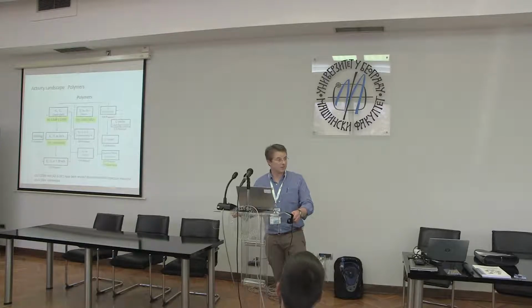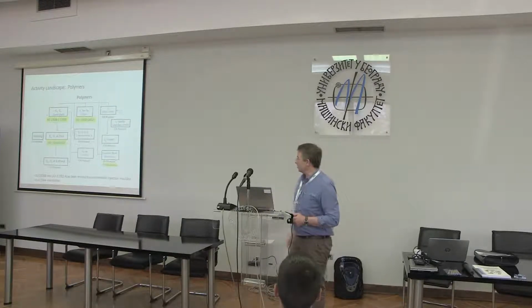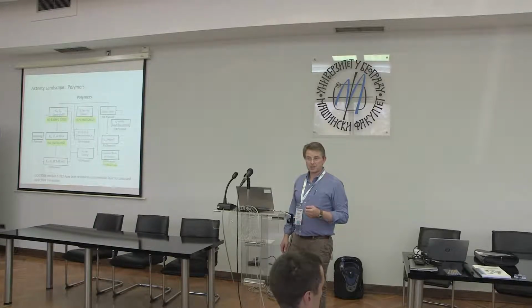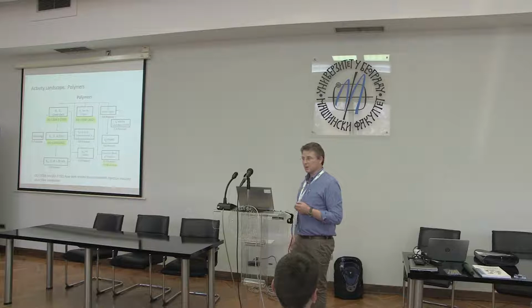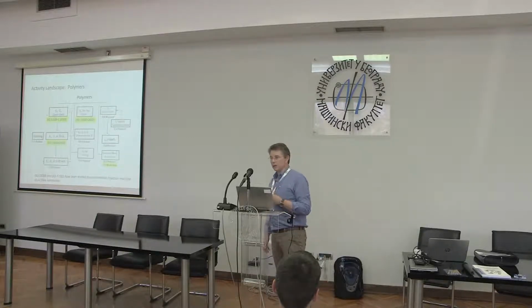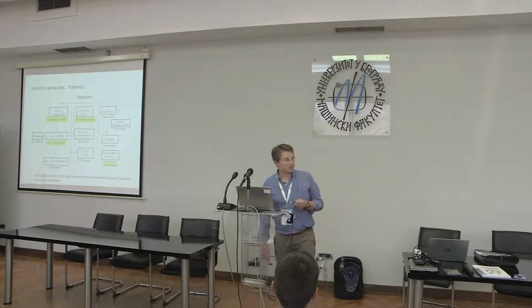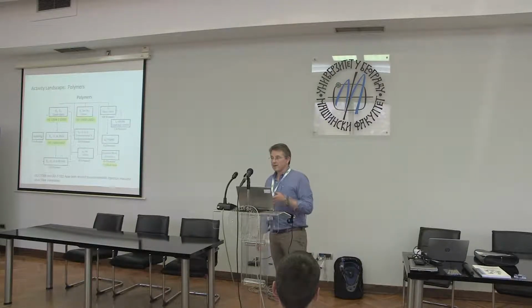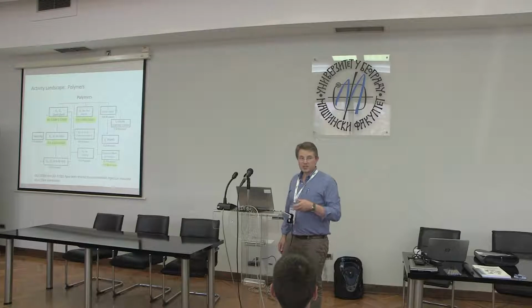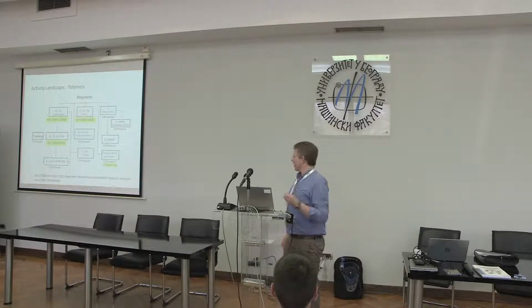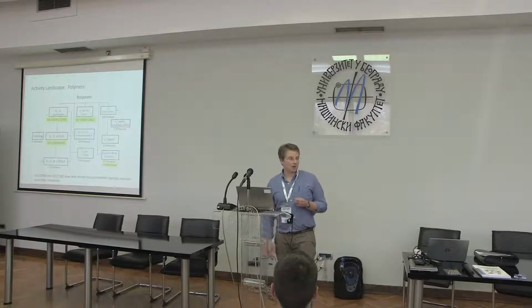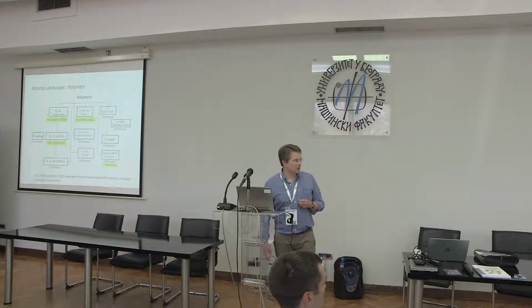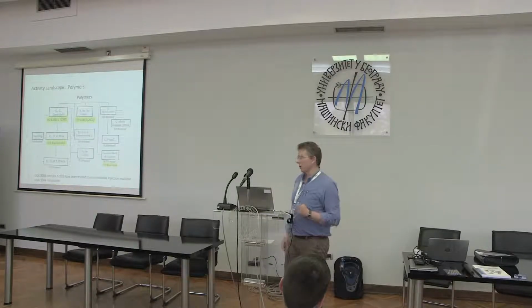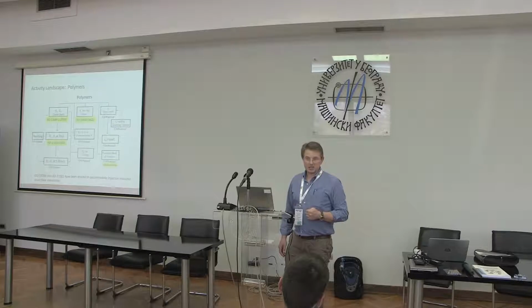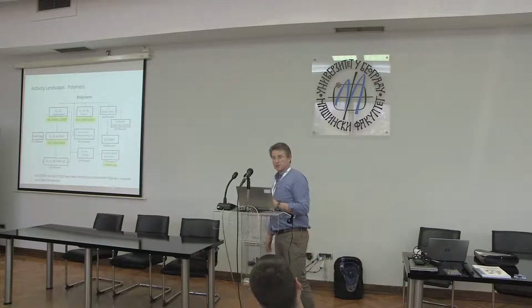Now, this is a variant of J, but it's for a plane stress condition, so it's basically applied to polymer films. It's a double-edge notched specimen, thin film. The idea is to generate a complete plastically deformed ligament in the center of the material and effectively measure how much energy is dissipated by growing the crack from the edges through to the center. Again, that's a method that is intrinsically quite simple, but has been enormously difficult to obtain reproducibility between different labs. So the technical committee has been working on that method for in excess of 10 years, trying to evaluate why that reproducibility is not there.